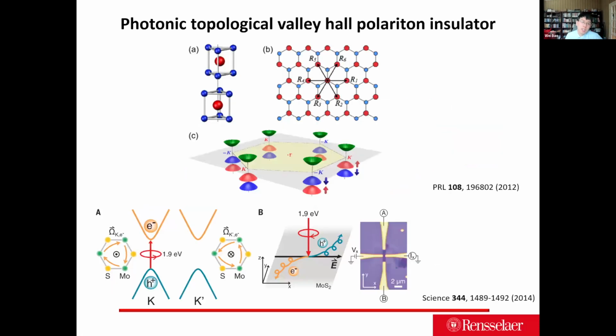So facing those challenges, we got a lot of inspiration from the topological valley Hall designs. Essentially, the topological valley Hall design we got directly from the 2D community. In the 2D community, once you break the symmetry of graphene, so essentially you make graphene have two different atom sizes, you start to make the Dirac cones' valleys become symmetry breaking. So you have a K and a K prime valley because you have different atom sizes.